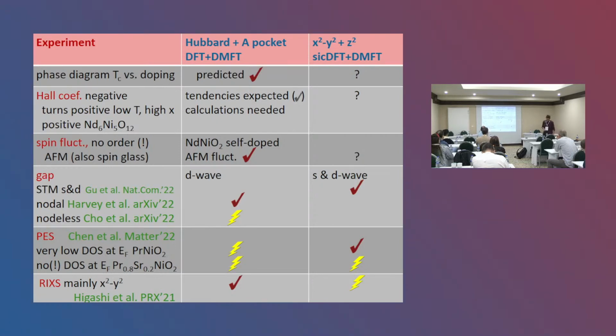And then there is quite some discussion about the gap. So we clearly have a D wave, Frank also gets S wave, and in experiments there is also a different experiment, even based on the London penetration depths. Ariando and the group of Harold Wang arrive at different conclusions there. Then there is no RPES. RPES would be, of course, a good way to discriminate between different theories. There is a photoemission spectrum, but that is, in my view, a little bit suspicious because there is no density of states even for the doped compound, which is clearly a metal, which is getting superconducting, and therefore we are for sure in disagreement with this photoemission spectrum, and the RIXS I already mentioned.